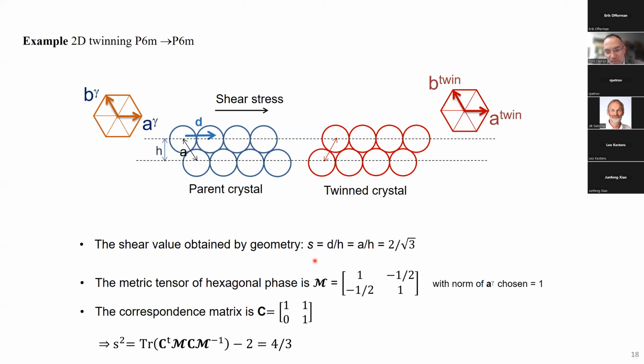Okay, you have to calculate the metric tensor. Here, for a hexagonal phase, it is given here. Okay, here it's -1/2 because you have an angle of 120 degrees between these two vectors. That's why the cosine makes a -1/2, and it's a symmetric tensor. So you can calculate quite easily the metric tensor. And the correspondence matrix is also very easily calculated. And then you apply the formula, and it gives you that the shear amplitude is exactly as you have found by geometry. But here, this approach works in any case, even the very complex ones.